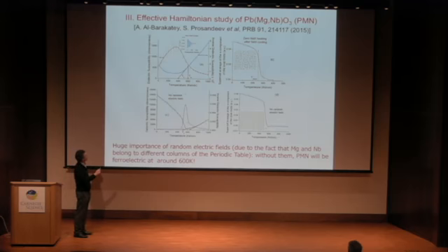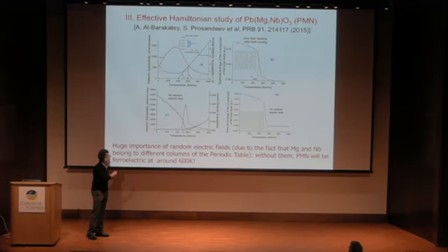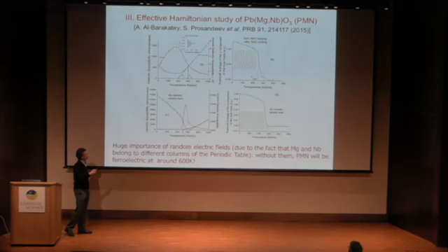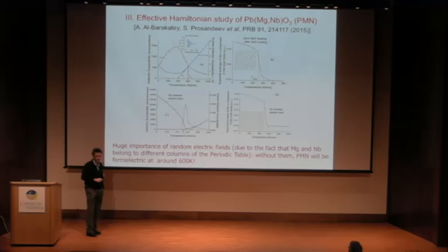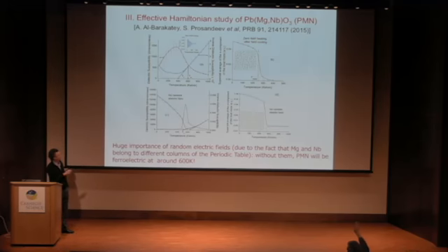So let me show you some results: dielectric response versus temperature. We see this dielectric peak, but what we found is that below this temperature, it's still paraelectric. If you look at the inverse dielectric response, it shows that below the Burns temperature, around 600 K in the simulations, and not too far away in the experiments, you deviate, so you have this Burns temperature.